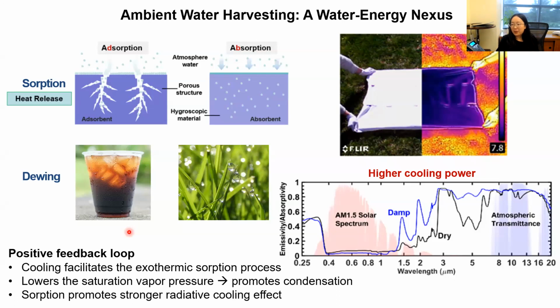And in this project, we use a radiative cooling fabric. It's passive cooling, so you don't have to have any energy input. The passive cooling happens spontaneously by facing the fabric to the sky. This cooling helps with both sorption and dewing. It facilitates the sorption process and lowers the saturation vapor pressure so that it can promote condensation. In turn, after the cellulose fabric grabs the water, the water enhances the infrared emission so that it can promote a stronger radiative cooling effect. So this truly gives us a positive feedback loop for a desirable performance.